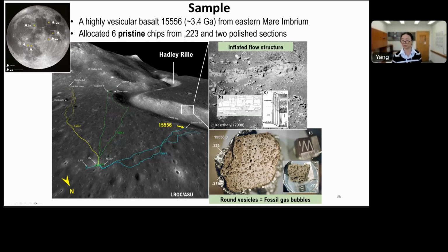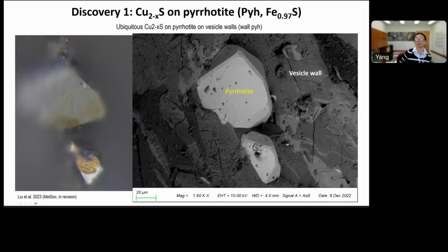The sample we looked at is actually a very small chip coming out of this subsample .223. We also have 2 thin sections made from this rock in order to compare what we see in 3D with 2D data. Okay, so here is the first discovery. We found copper sulfide on pyrrhotite in this sample. I think copper sulfide has never been reported before in lunar samples. And the occurrence of the copper sulfide is very ubiquitous. So all the sulfides we see in the sample have more or less been coated by copper sulfide.